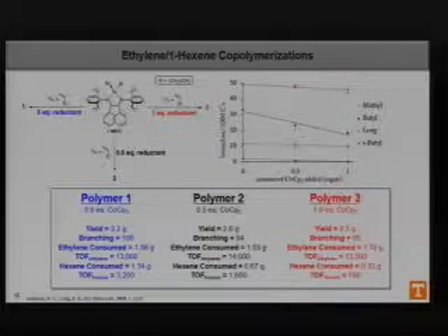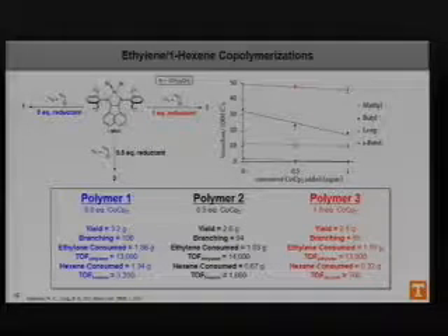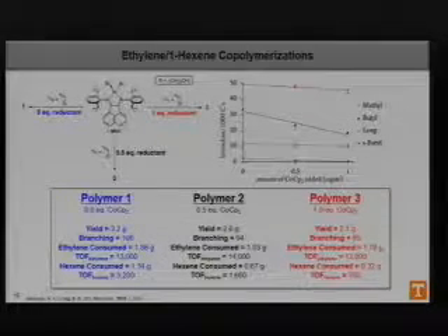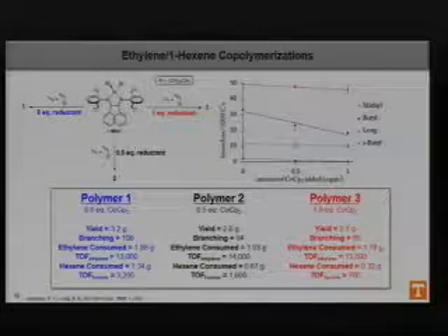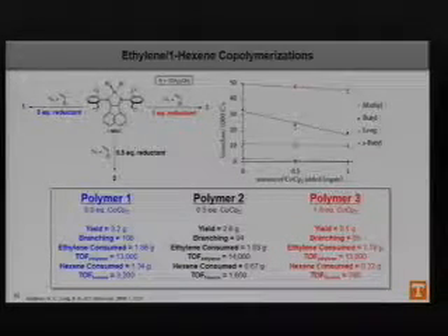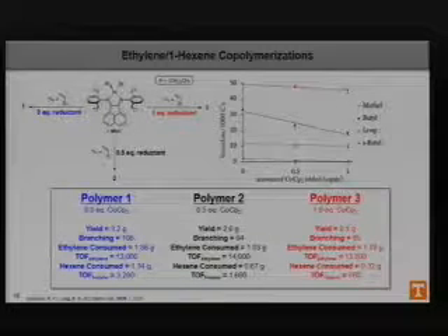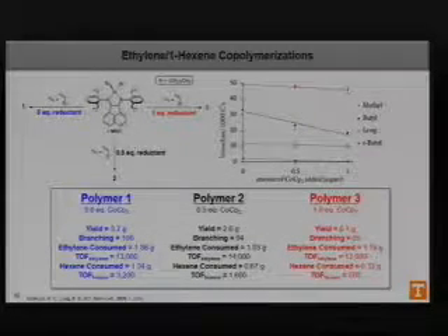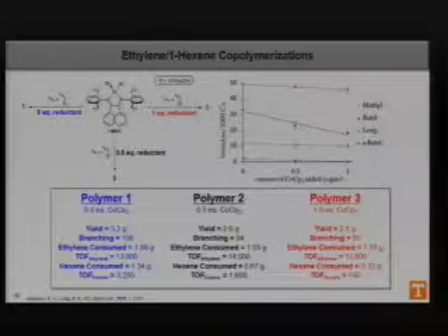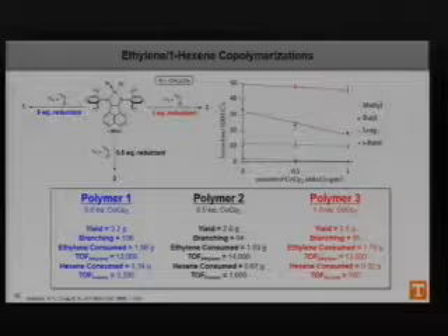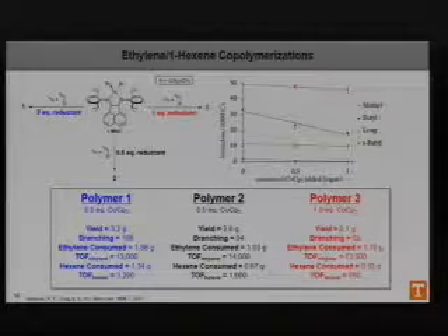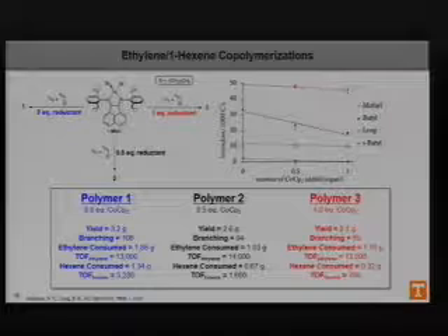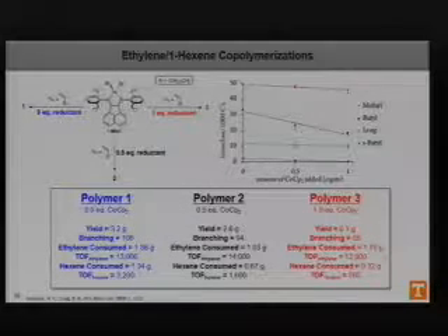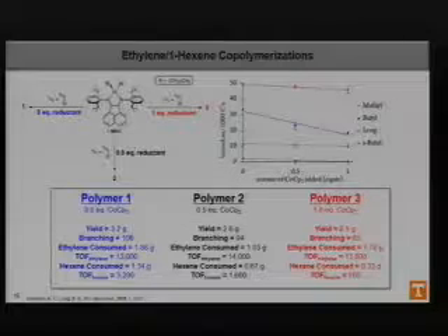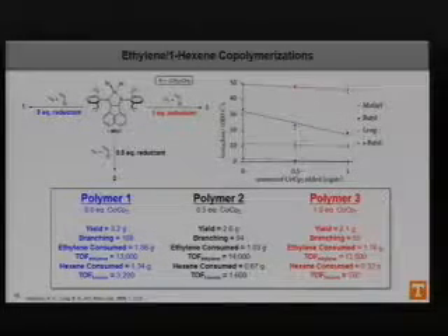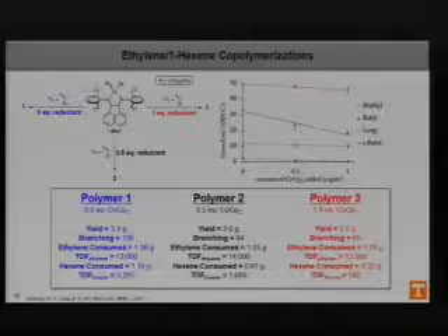Now, if we looked at the other polymer results for these 3 samples, we found that the branching, like I mentioned before, indeed went down. The yield went from 3.2 to 2.1 grams, so that's a significant decrease. But the ethylene consumed was about the same in each of the 3 scenarios. So what in fact was happening was the hexene consumed went from 1.3 all the way down to about 0.3 as we increased the equivalents of reductant. So we in fact were creating a system in which we could decrease and change the comonomer incorporation rates.